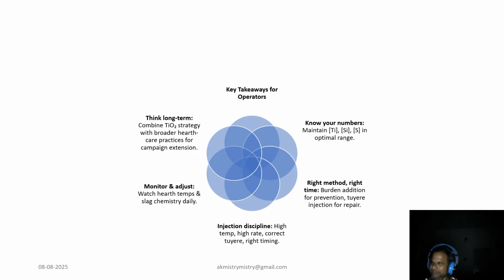To summarize, track your Ti, Si and sulfur. These dictate TiCN formation. Choose the right method: burden addition for long-term prevention, tuyere injection for urgent local repair. Follow injection discipline; correct timing, tuyere location and high hearth temperature are essential. Monitor results and adjust daily. Finally, think long term. Combine TiO₂ with broader hearth care practices to get the longest possible campaign life.